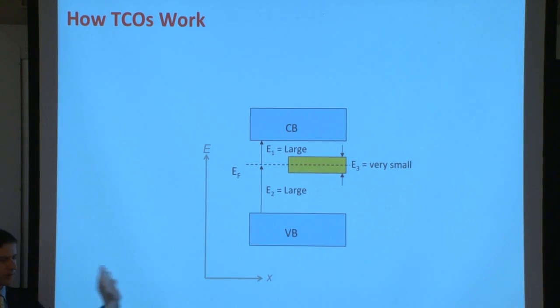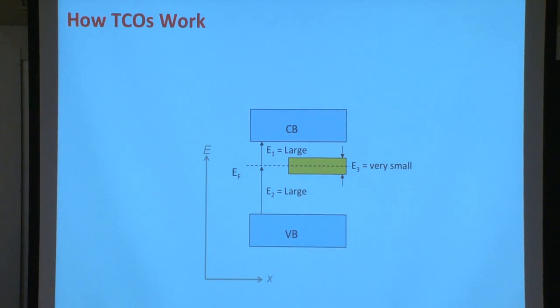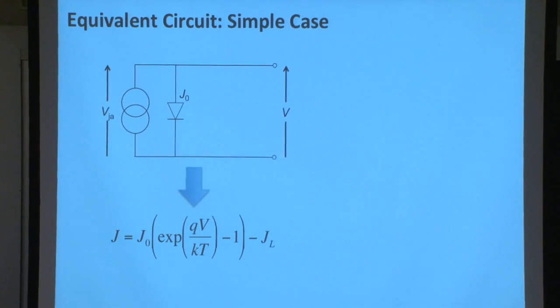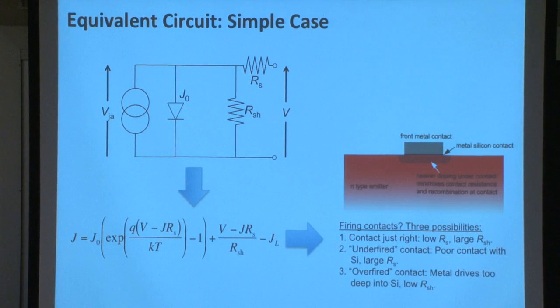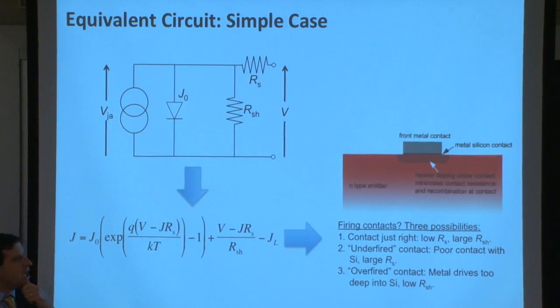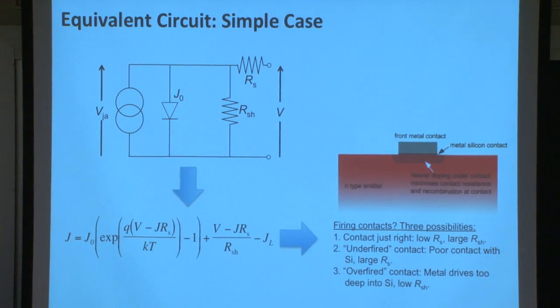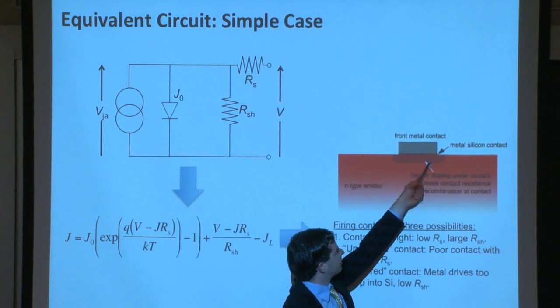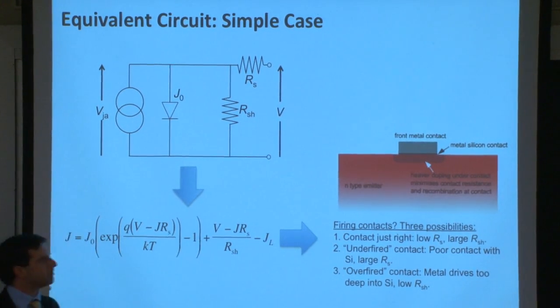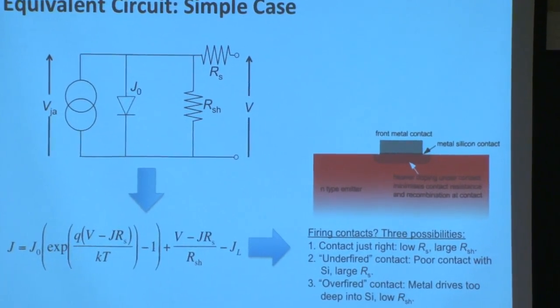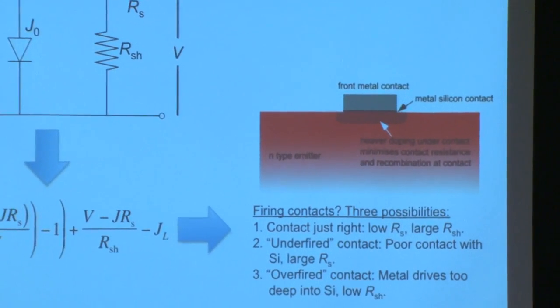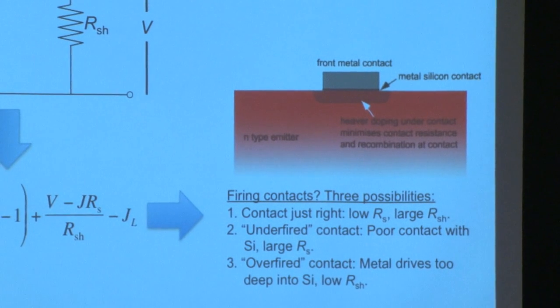I'd rather not generalize about them. About metals, it's more straightforward. Okay, I guess then for metals, you would have to choose a metal that melts before your semiconductor melts, or typically you wouldn't have your metal melting per se. What you're looking for is a chemical reaction here at this interface. You're looking for the metal most often to form a binary compound between your metal and the semiconducting material underneath.